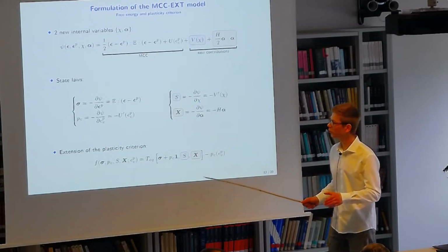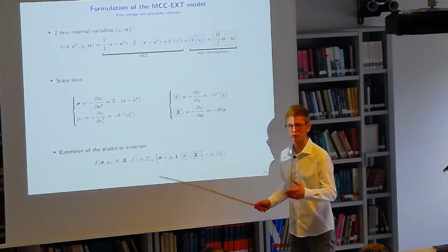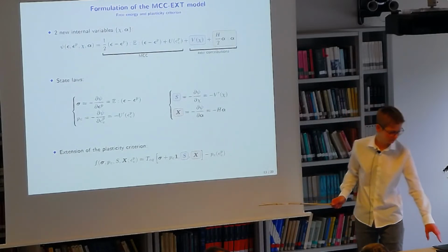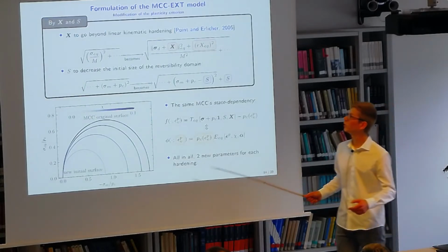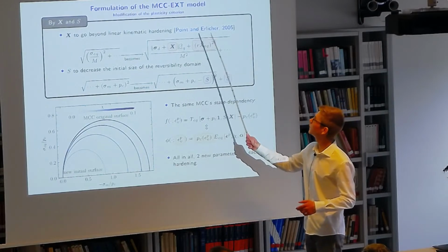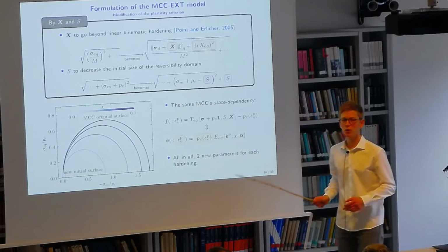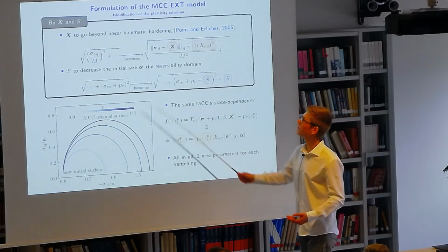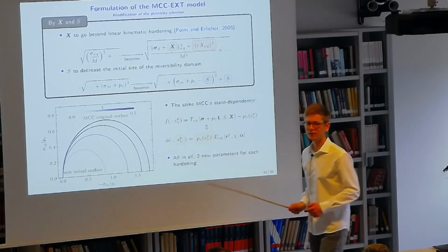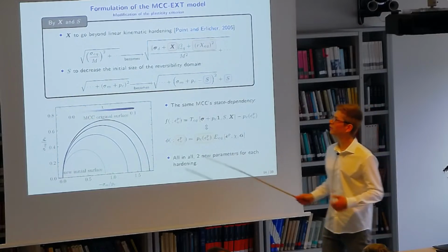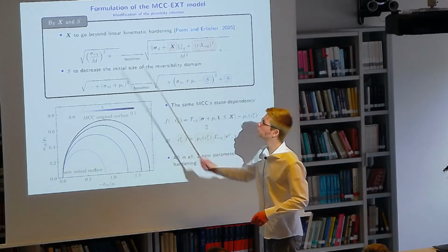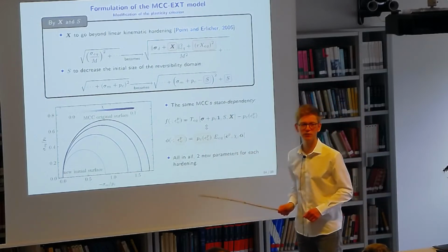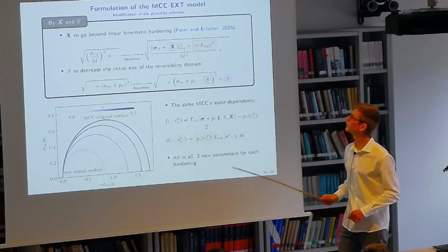In this extension, we were quite inspired by other approaches in order to model similar elements, but for other classes of materials. The first was motivated by a work proposed by Nelly Point and Silvano Erlicher, who tried to introduce nonlinear hardening by going beyond the linear kinematic one. In their approach, in the yield criterion, the equivalent stress is replaced by a combination between the deviatoric part of the stress and the new force X.